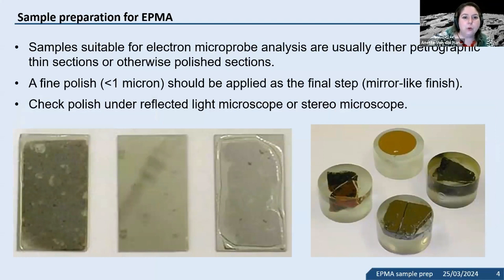Okay. So as I mentioned, they all need to be flat and polished, but otherwise there are a couple of different form factors that you can find. Thin sections, and 1-inch epoxy mounts where you just embed the materials, are also very popular because you don't have to hit the target thickness like with a thin section. And there are sometimes also other holders where a surface can just be polished, and you can use some kind of vise to bring it in. The downside of that is often that it makes it more likely that the sample is tilted. And usually a good microprobe sample holder is top referenced to minimize any sample tilt.